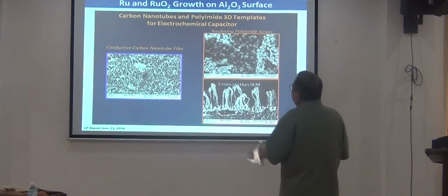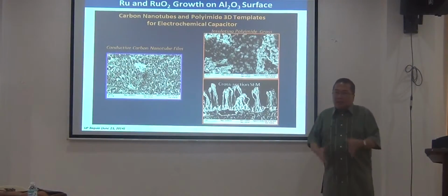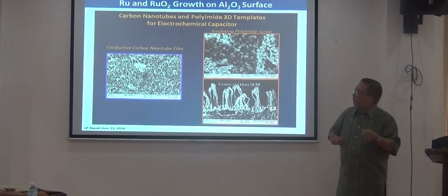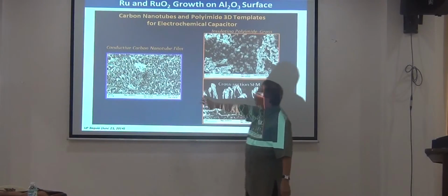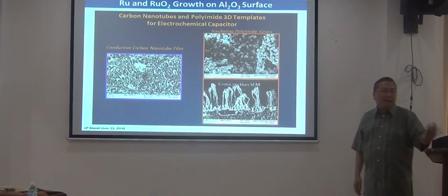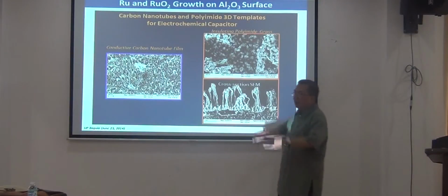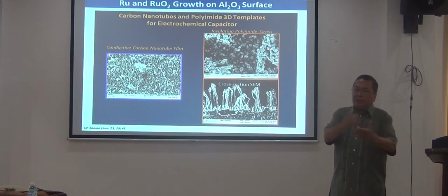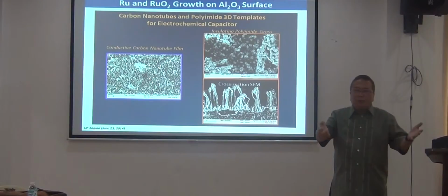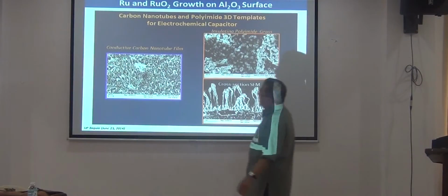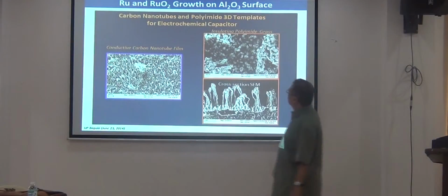Now, if you want to increase the capacitance, as I said, these electrodes require three-dimensional structure. We explored two types of structure. One is just carbon nanotubes. So basically, this is just a spaghetti of carbon nanotube. So it's commercially bought, and that's dispersible in water. So you just spray it, and then to make a nice three-dimensional film that's illustrated here.